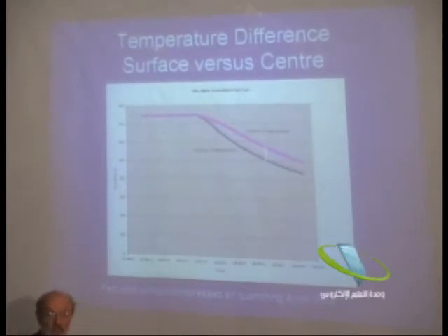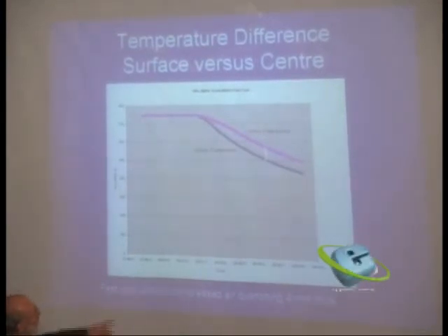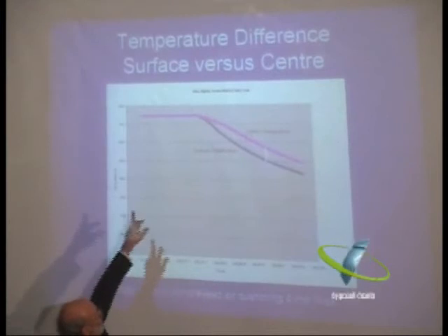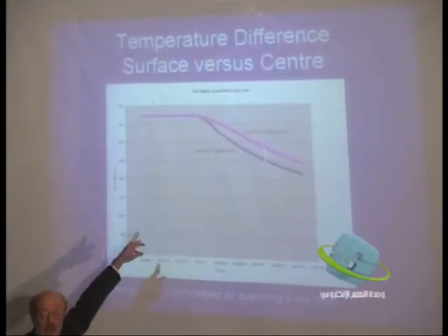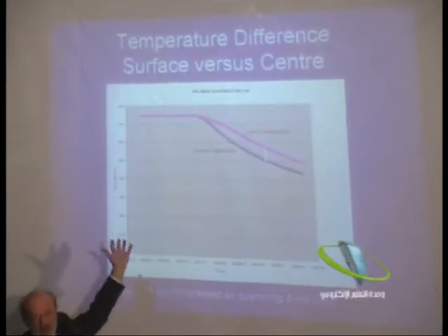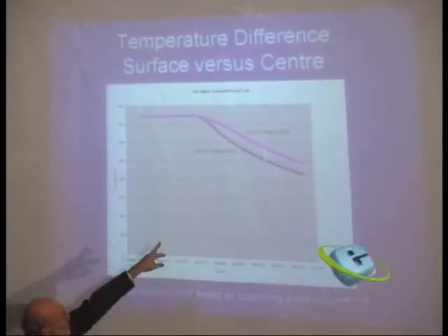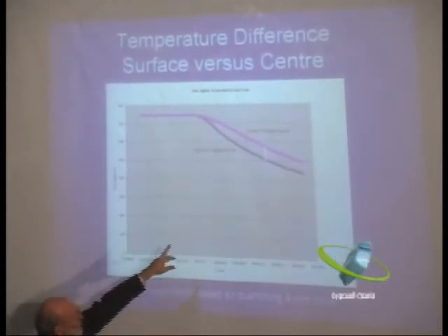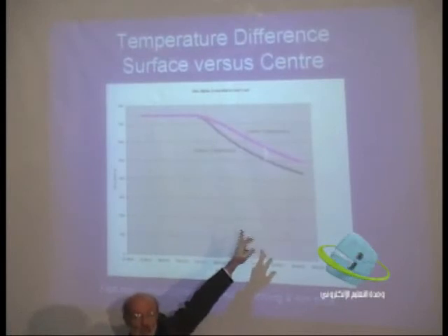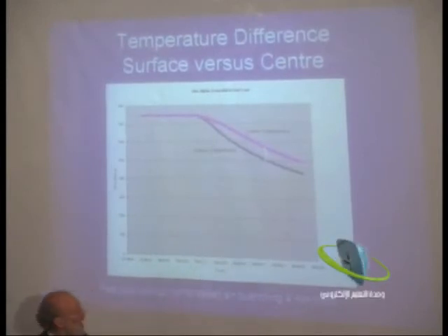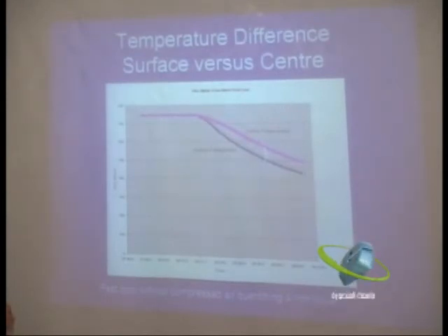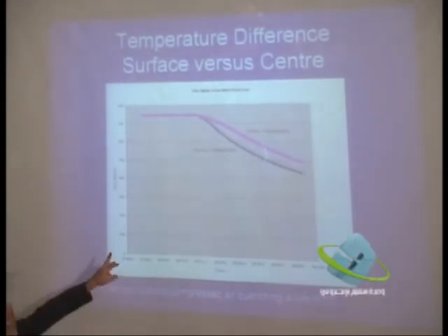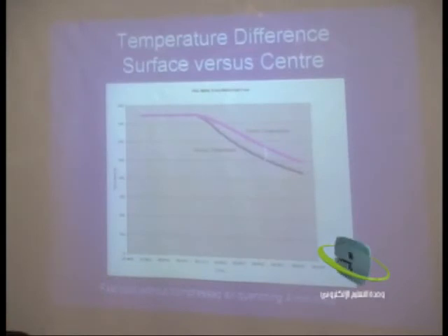And what do we see? The temperature difference. So here is where we have the temperature difference on the inside. So at high temperature, there is no difference in the furnace. Now when we pull it out of the furnace, you see this difference. The outside or the surface temperature is much lower than the inside. And that's because of the poor thermal conductivity of that system. I know of other people that have measured temperature differences exceeding 150 degrees centigrade because of this rapid cooling.